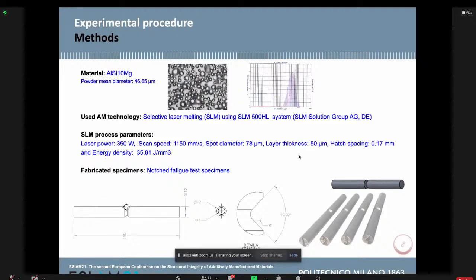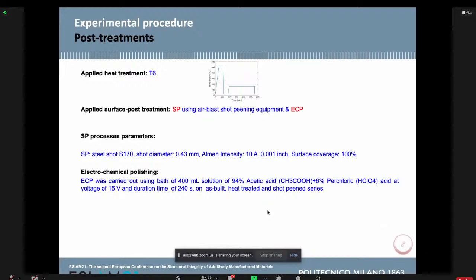Here you can see the parameters of the LPBF process and also the shape and dimensions of the notched fatigue specimen. In the design of the notched fatigue specimens, a notch root radius of 1 was considered to ensure that we can reach the notch root by impacting the shot media. Then we applied T6 heat treatment on the material for homogenizing the microstructure. Then we used shot peening with steel shots with Almen intensity of 10A and full surface coverage of 100%. And also we applied electrochemical polishing, ECP, using